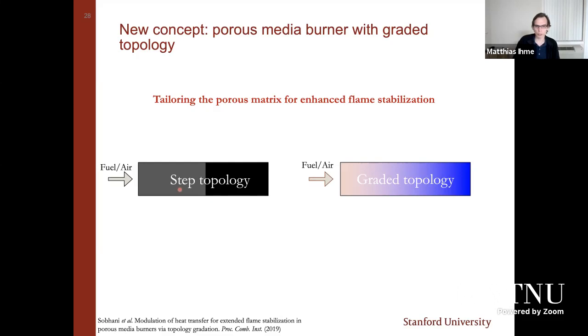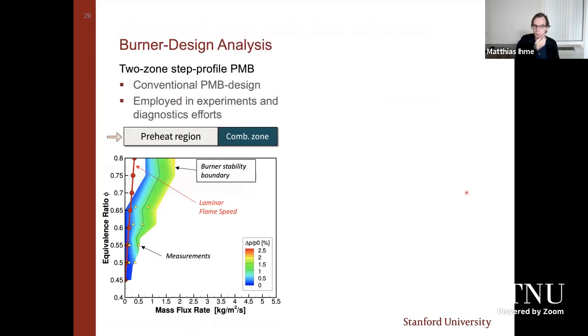So here I'm contrasting the step or two-zone burner, where we have this preheat zone and this combustion zone, against this graded topology, where we're continuously changing the pore diameter and the porosity throughout the burner. Again, looking back to the stability diagram, plotting the equivalence ratio as a function of the mass flow rate, this colored region here is the stable operating point. I'm showing here some measurements in yellow, just to confirm that this simulation result is essentially verified and validated. And for comparison, I'm also looking at a free flame system.